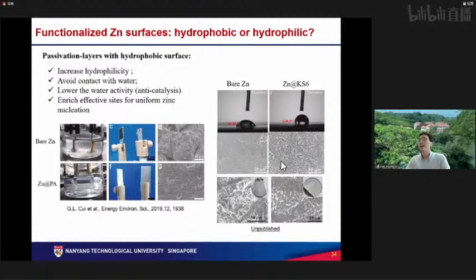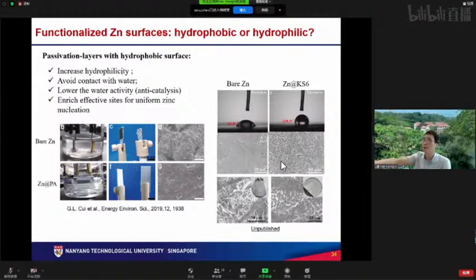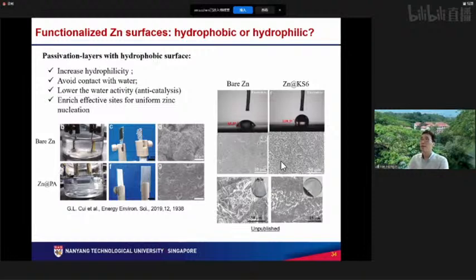Okay, the multiple factors I try to summarize here. You may increase the hydrophilicity of the water electrolyte. You want to have a good contact, and it may avoid the contact with the water directly. You coat the surface so the zinc surface will not directly contact the water, and it lowers the water activities. Okay. So if you increase hydrophilicity, that means what? That means there are more electrolyte ions that can come to the surface and penetrate through your passivation layers. So you must have good ion conductivities. And also you increase the effective surface sites for uniform zinc nucleation.